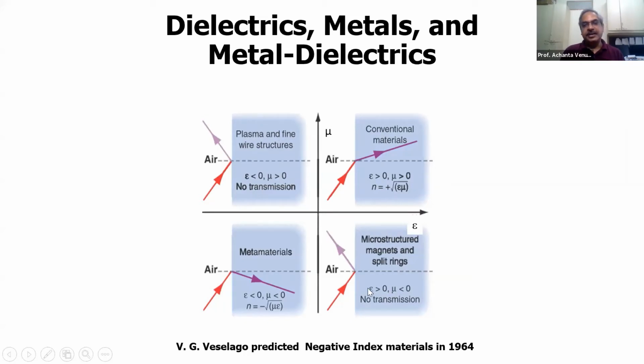Similarly, in the fourth quadrant, you have epsilon greater than 0 and mu less than 0. You can get these with magnetic microstructured magnets and split rings. But the interesting point is in the third quadrant, where epsilon is less than 0 and mu is less than 0. Both are negative, which leads to a negative refractive index. Metamaterials were initially considered to be negative index materials, which have unique properties. For example, the Doppler shift is opposite: when the source is approaching us, instead of the frequency increasing, as we see when n is positive, in a negative index medium we see the frequency decreasing.